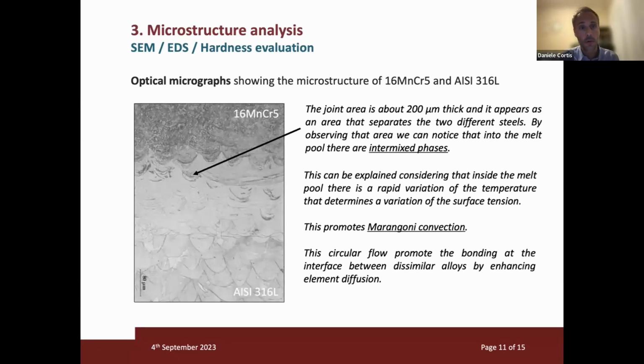Then here, always with optical analysis, there is the image of the junction. The junction is about 200 microns thick, and you can see some intermixed phase between these two materials. These intermixed phases are probably generated by a variation of the surface tension. This variation of the surface tension promotes the generation of mass flow, also known as Marangoni effect convection, which is also an effect that can enhance the bonding between the two different materials, in this case between these different steels.